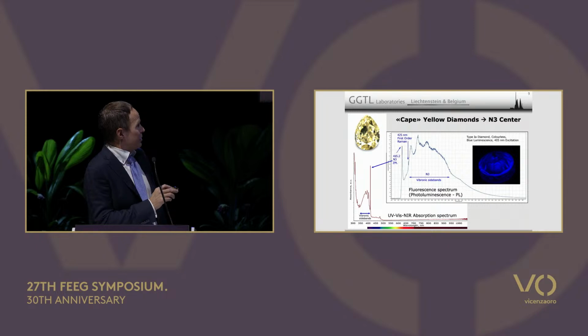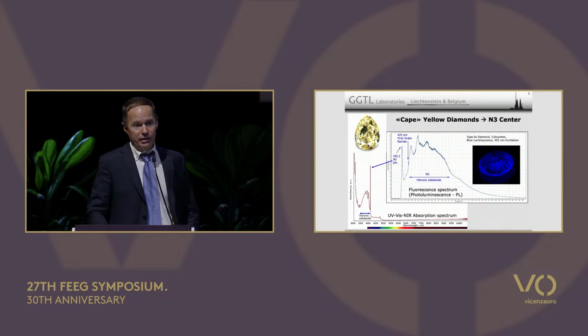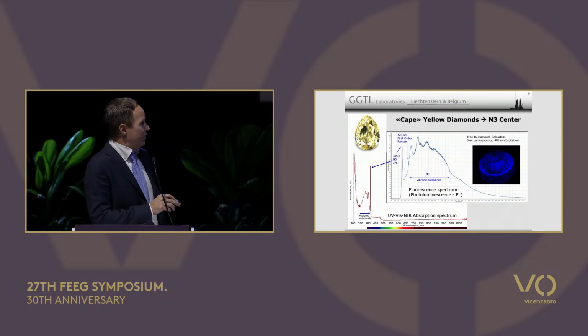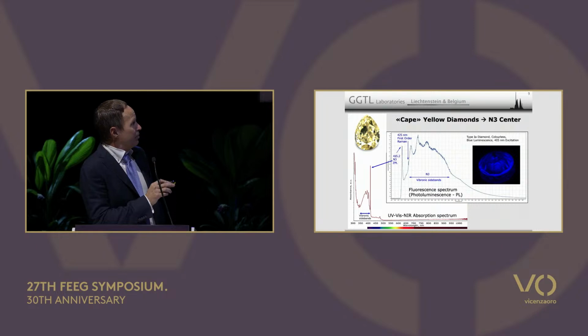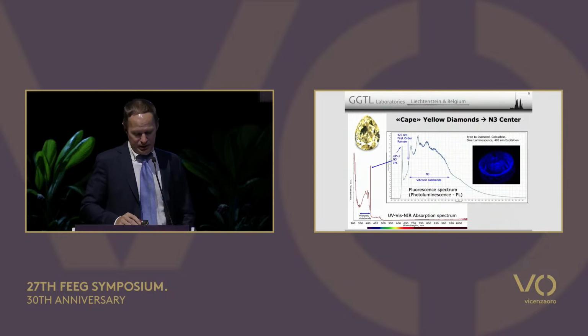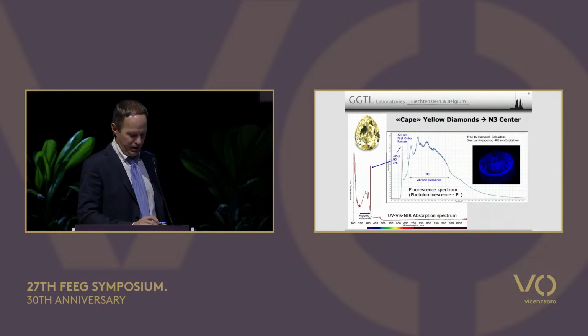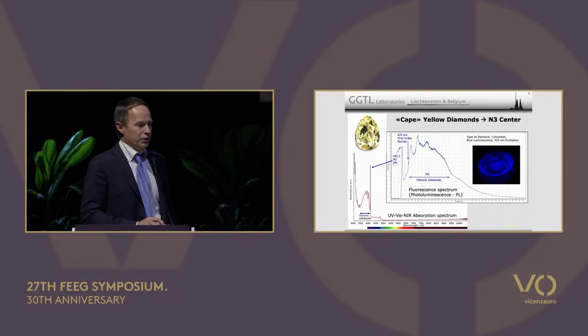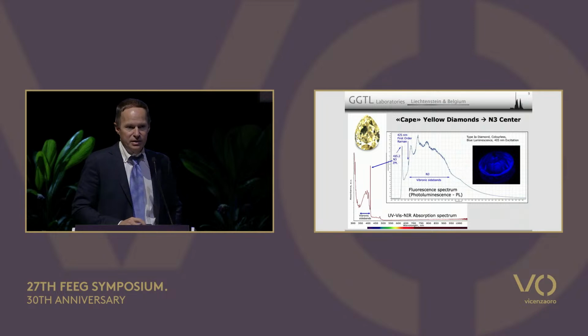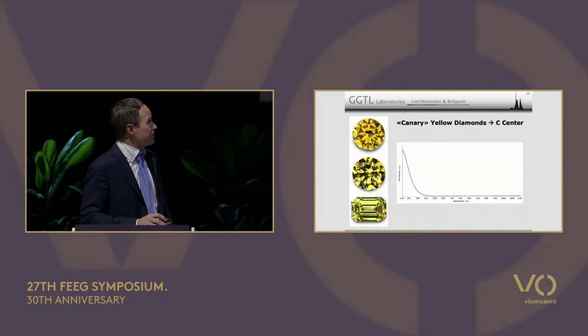The Cape spectrum is this one here. This is an absorption spectrum. The Cape line is this 415 nanometer band here. It causes yellow color and blue fluorescence. That's a very common defect that we rely on heavily in the identification of synthetic diamond, for example, because it never occurs in very strong intensities in synthetic diamond, at least not in colorless synthetic diamond.